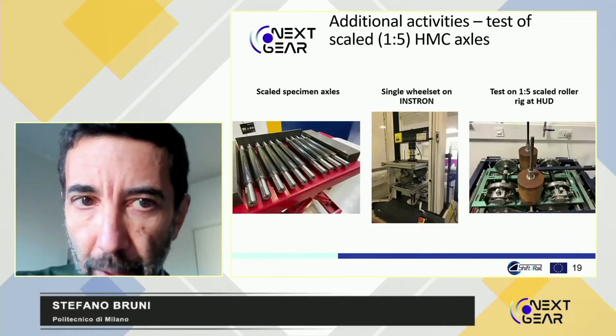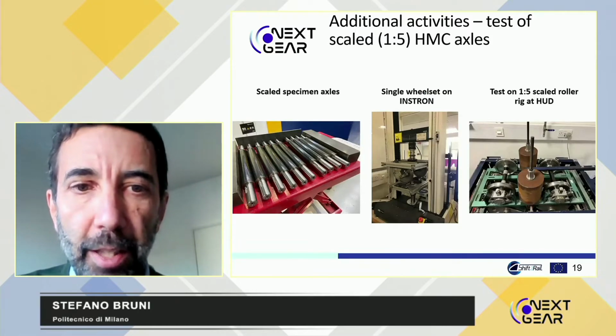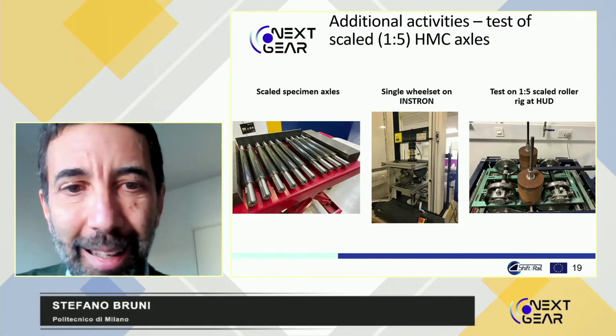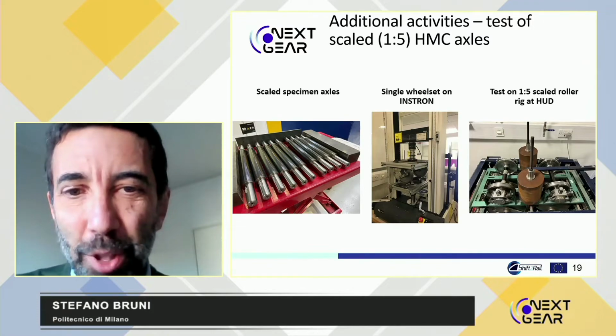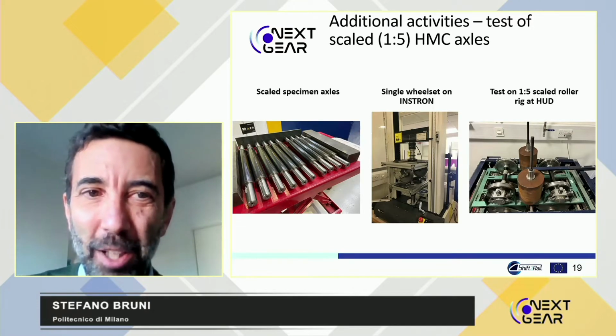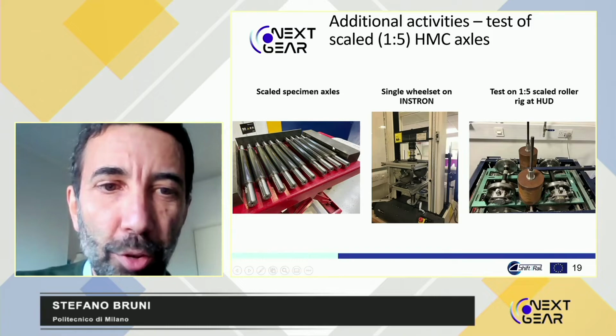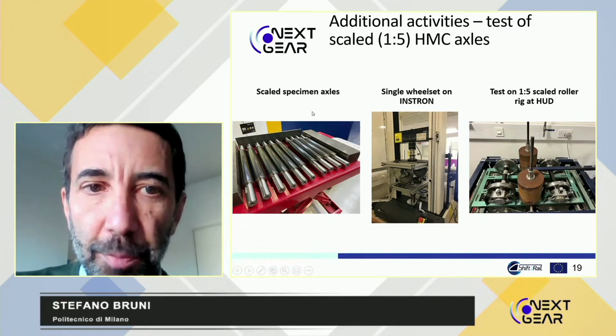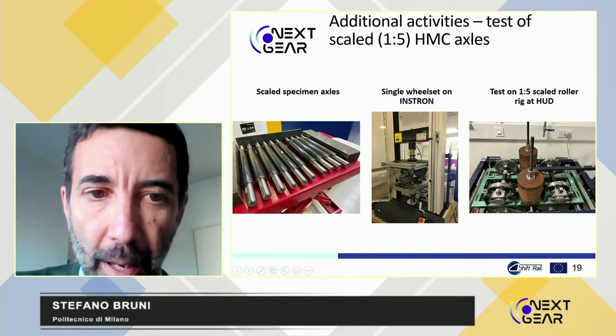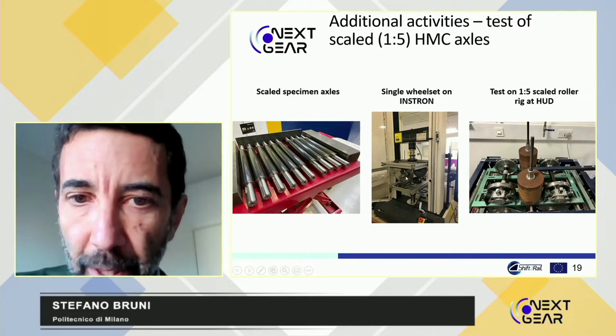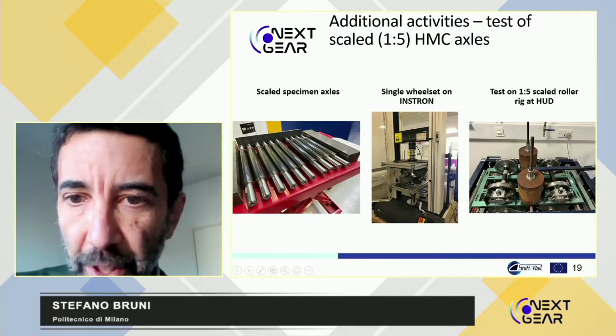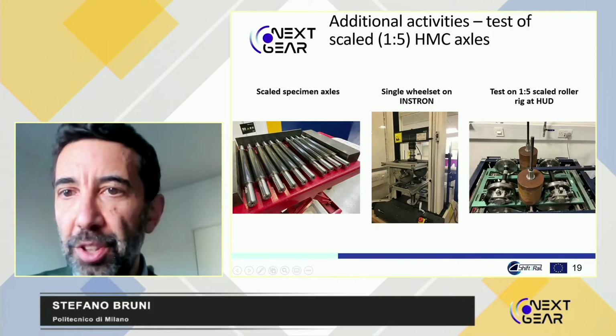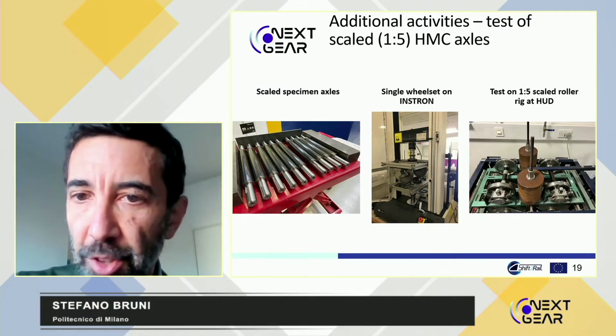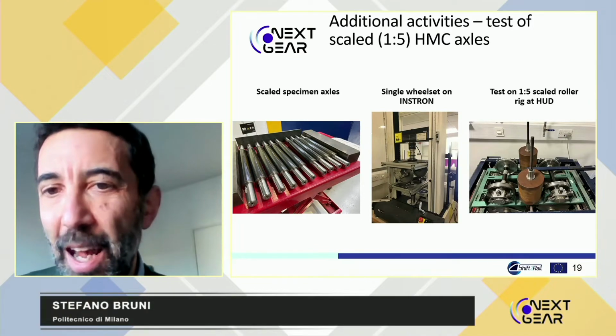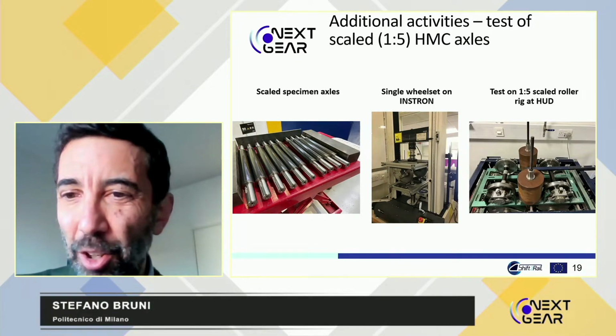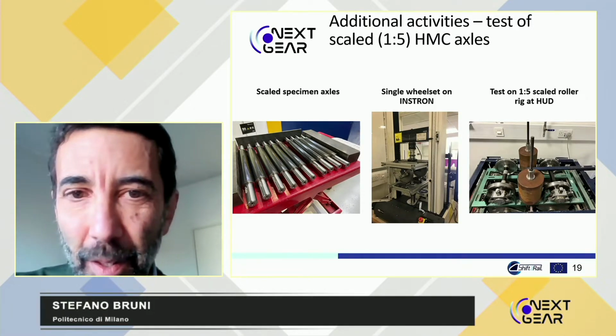Just want to mention very quickly that we also had a demonstration phase, which was not initially foreseen as part of the project, but we were able to produce some scaled 1-in-5 specimens of the composite axles and test them on a single wheelset, as you see here, and then on a scaled roller rig, which is available at Huddersfield University, to show that actually the concept is feasible.